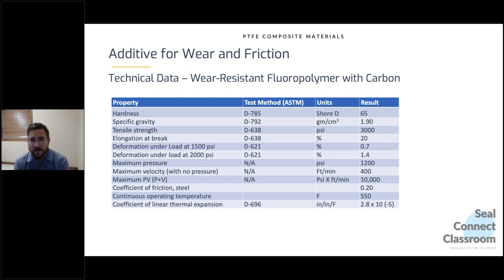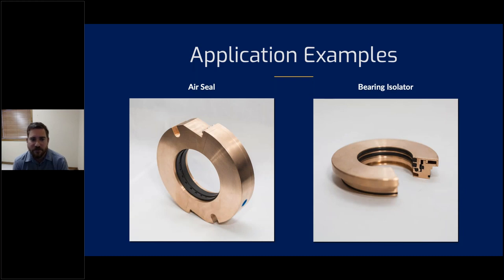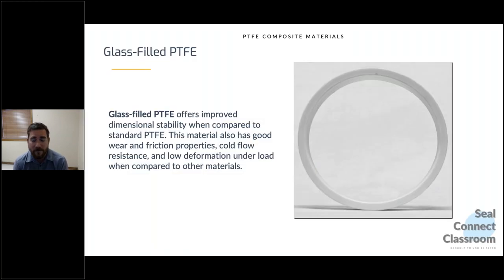And the coefficient of linear thermal expansion. So that was the question that you just had. What does the material do when temperature rises? This particular material, the carbon fiber bolsters that and makes it much, much better. So as comparison to a virgin PTFE, this is a third of that thermal expansion. So yeah, you can take a peek at that at your leisure. But some broad applications of these wear and friction grade materials: air seals, the throttle for an air seal, bearing isolators. But really, any material where there's metal mating surfaces or the components are going to be rubbing together, this is a fantastic wear and friction material. So even things like piston rings and stuff, this would be an option.